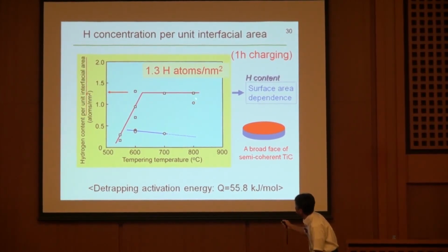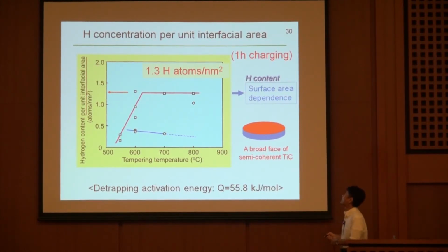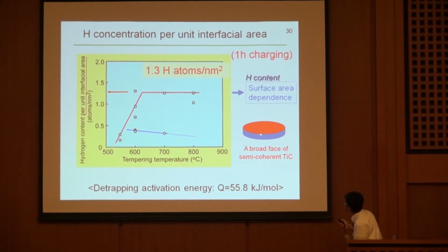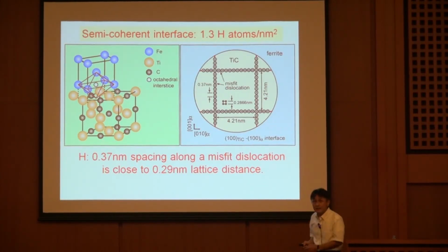So then something is here, okay, with this value of 1.3 hydrogen atoms per square nanometer. In this case, we took many TEM photos, found the size of the carbide, and obtained the surface area in unit volume of a sample. And also we found the detrapping activation energy is like this. And what's the meaning of this? It should be related to the sites of hydrogen trapping.